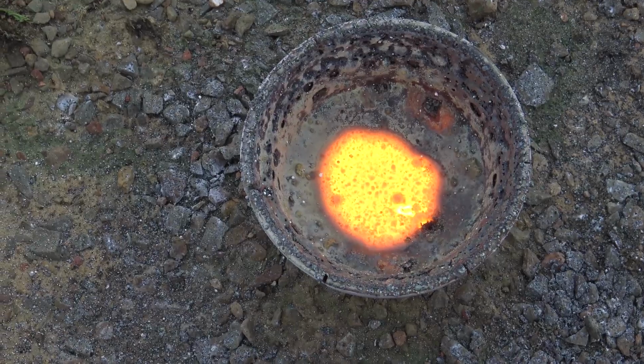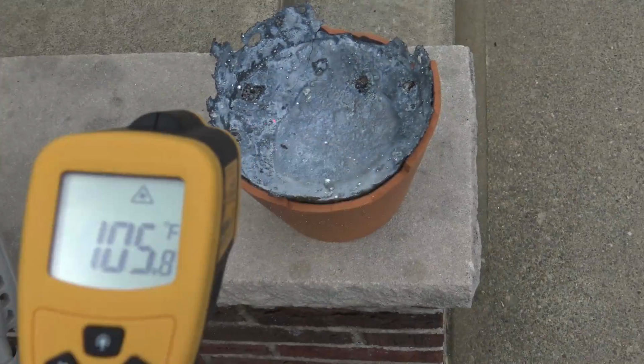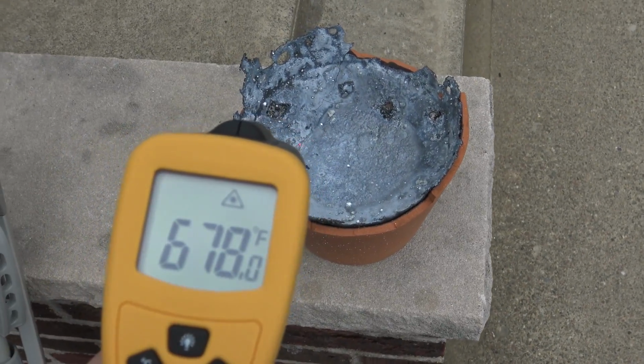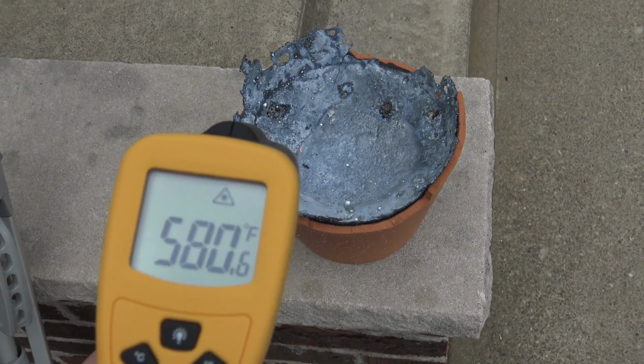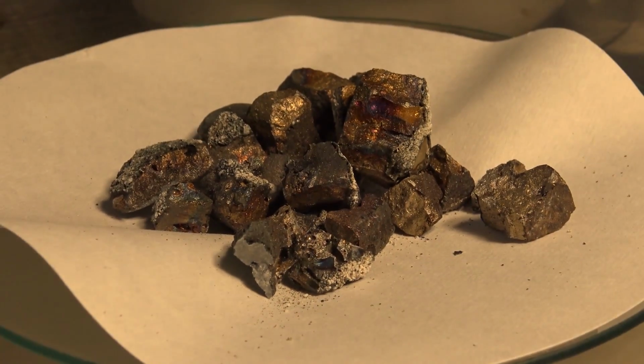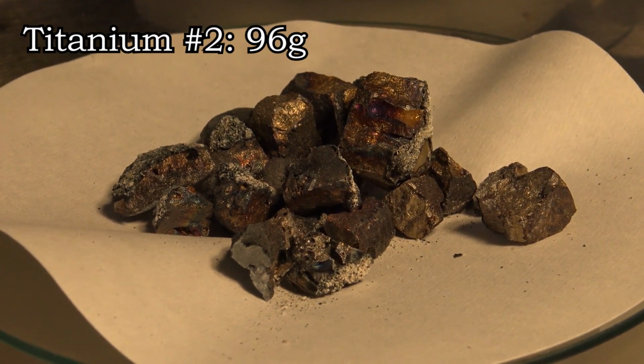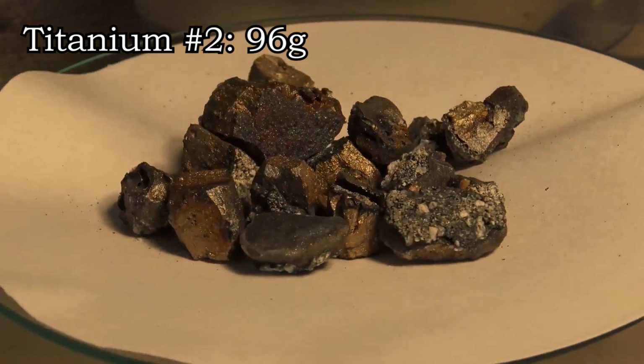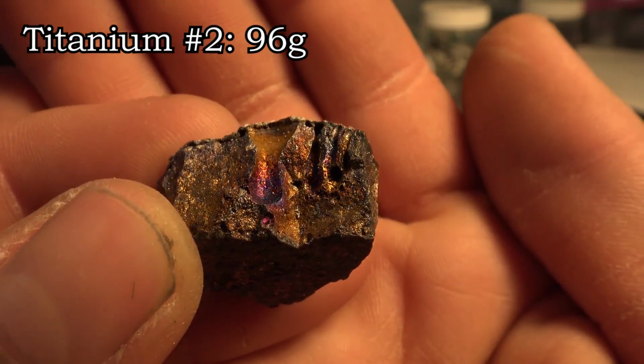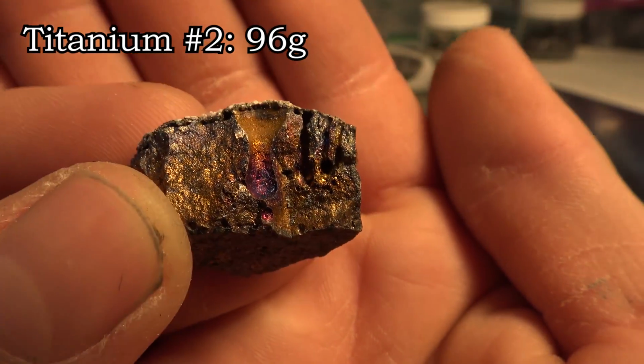Seemed to work fine to me, so let's break them open and find out. The titanium this time managed to separate from the slag and formed some very interesting colorations on the inside. The total weight extracted for the titanium is 96 grams, so not a very efficient process. The sparks you saw during the reaction was all the potential metal being thrown out of the pot.